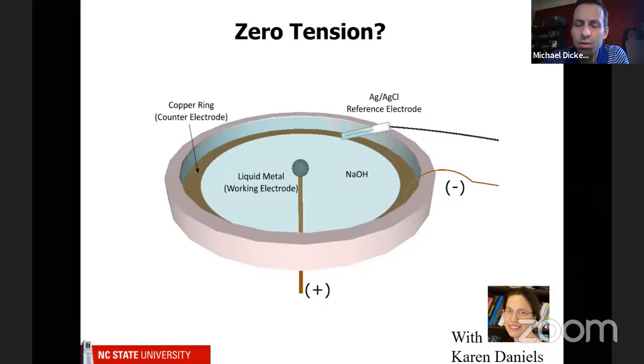So what we're doing is we've got a droplet, and I don't remember the exact diameter, but it's maybe 2 or 3 millimeters. It is sitting on a very flat surface. We have to have this surface be flat because if not, the droplet will roll off one way or the other. And then we contact it with a copper wire from the bottom, and the rest of the circuit is a sodium hydroxide solution, and then there's a counter electrode that goes all the way around, so the current is going radially outwards. Although it turns out that doesn't really matter, but we did this to make it symmetric.